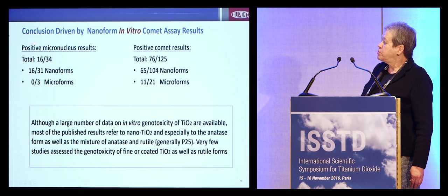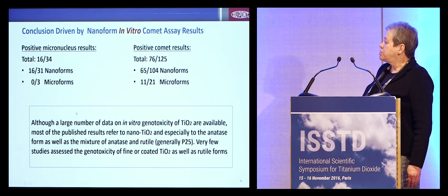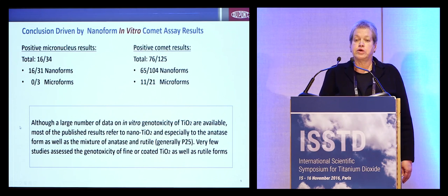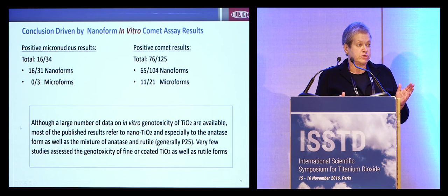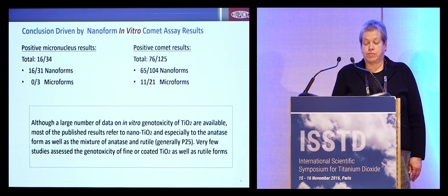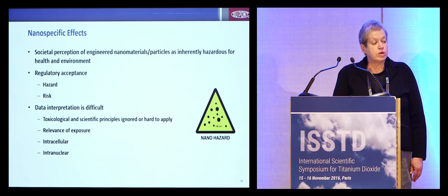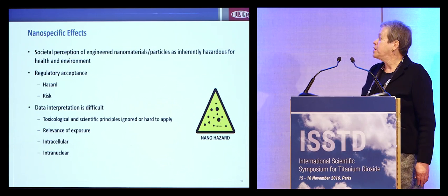There are also positive micronucleus results from the in vitro assays, but to a lesser extent; even there, about half were nanoforms. And here is a statement about the data and the forms of TiO2. All forms were taken together for the carcinogenesis evaluation. However, the genotox results were definitely driven by the nanoform. Nanospecific effects, do we have them? Yes and no. We don't know, I guess.